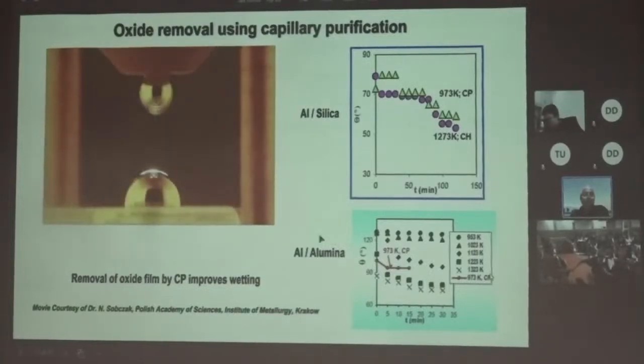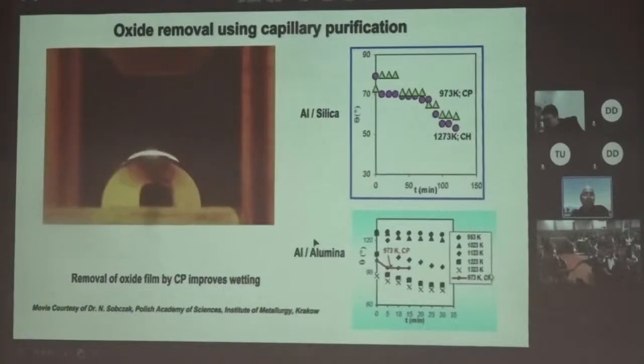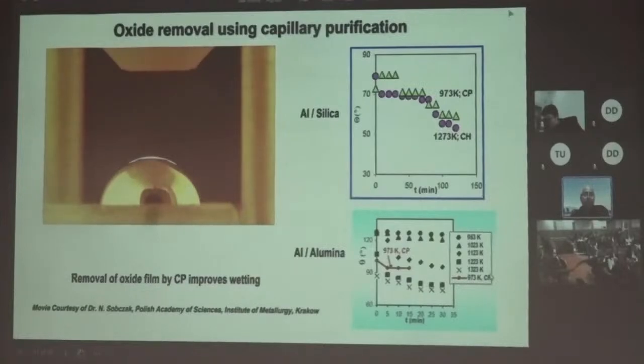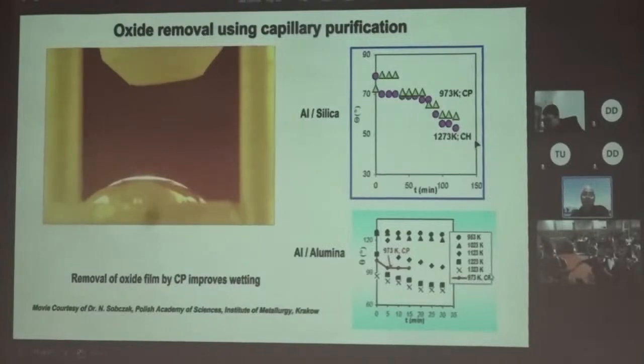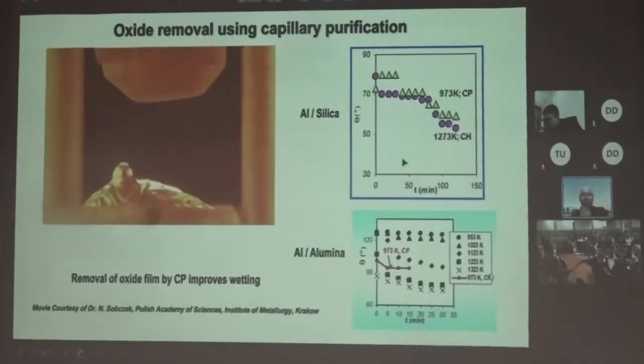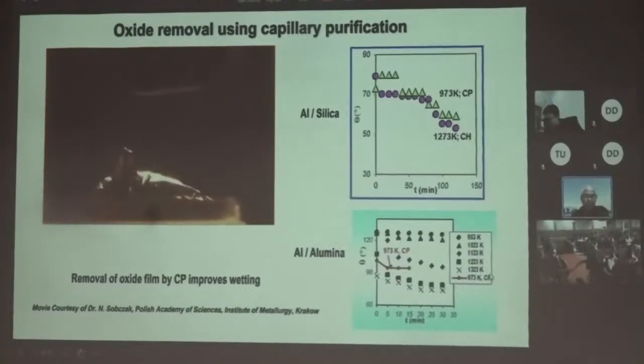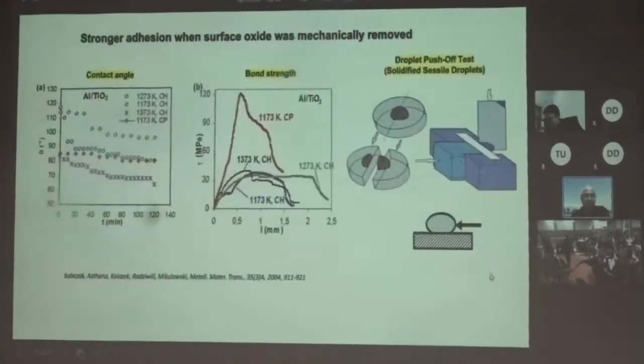So you're looking at a droplet that was squeezed out under high vacuum, and because of the squeezing action, the oxide on the surface was removed. And when you look at the contact angle data, even at low temperature, at 973 Kelvin, you're able to get the same low contact angle that you would have obtained at much higher temperature with contact heating. So what it shows is that a lot of things are happening at high temperature that we cannot really understand by applying the low temperature framework of wettability.